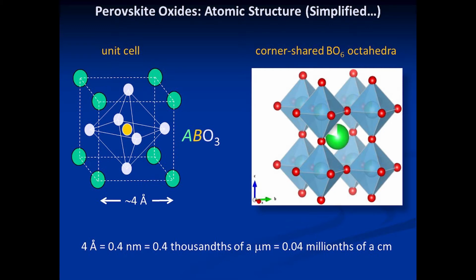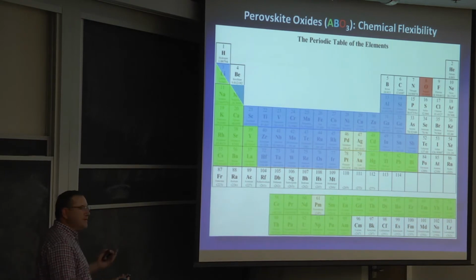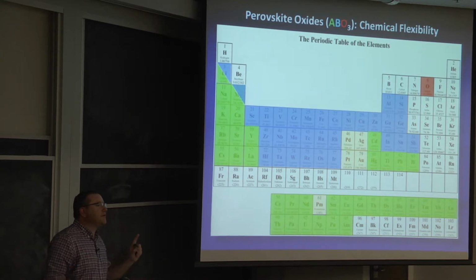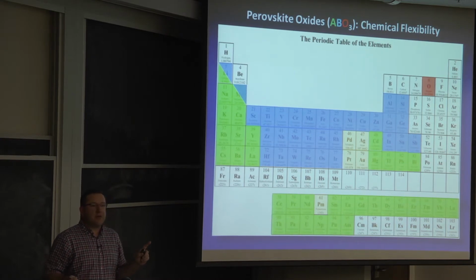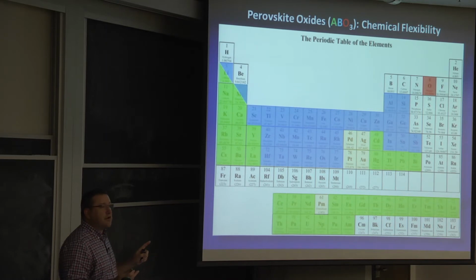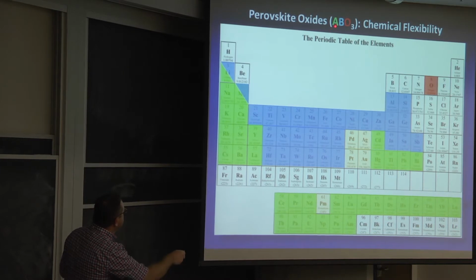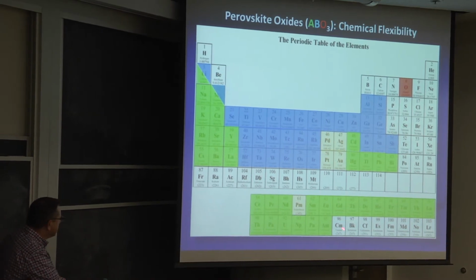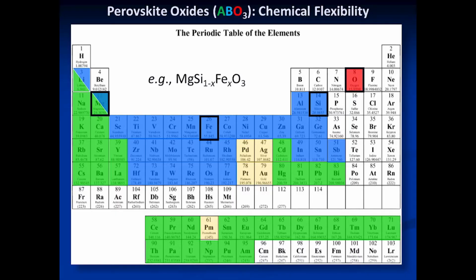So why do I like perovskites so much? Why do people like perovskites so much? Well, here's one thing about them that's pretty impressive, right? So even if I just pick oxygen, and there's a whole bunch of other stuff that makes perovskites, right? If you've read about recent things in the solar cell world, you know that you can also make organic, inorganic, hybrid perovskites, and they're extremely hot and very promising. But ignoring those, just take oxygen. If I paint green in the periodic table what I can put on the A site in a perovskite, and I paint blue what I can put on the B site, and then I ignore all the stuff that I don't want to work on because, you know, it's going to kill me in the course of doing the experiments, I have basically 3/4 of the periodic table covered. It's incredibly chemically flexible. There are many, many perovskites, lots of flexibility. That's a good start, right?